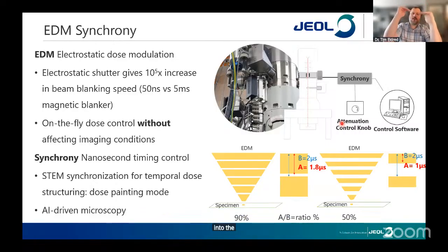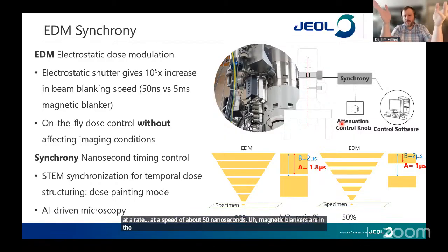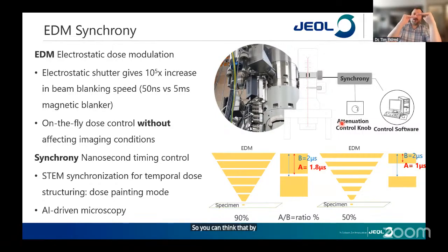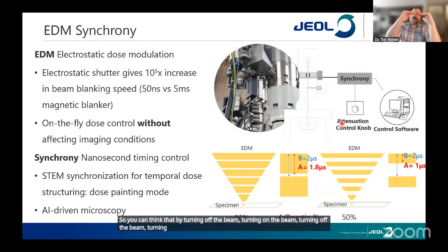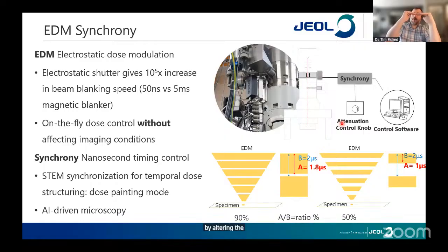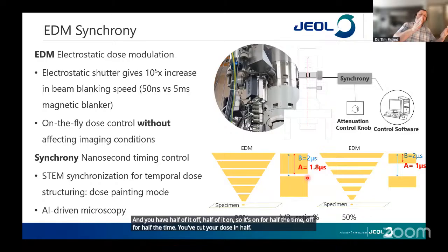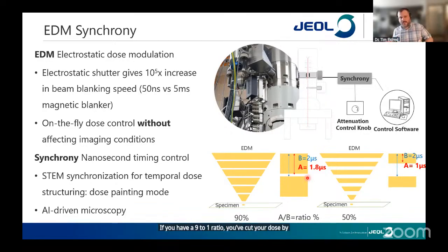So in the microscope, there's an electrostatic shutter that allows us to cut the beam at a speed of about 50 nanoseconds. Magnetic blankers are in the millisecond regime. So you can think that by turning off the beam, turning on the beam, turning off the beam, turning on the beam, by altering the ratio of on to off, these B to A pulses, you can decrease the dose by a proportional amount. You can imagine if you have a dose of A and you have half of it off, half of it on, so it's on for half the time, off for half the time, you've cut your dose in half. If you have a 9-to-1 ratio, you've cut your dose by a factor of 10.